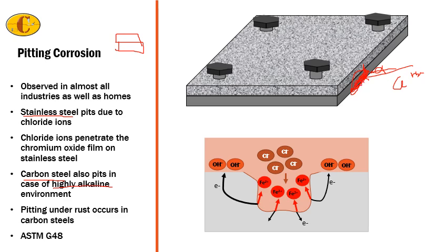In the other parts, however, the chloride can still continue going. So in this small part, you have the chloride reaching the corrosion site and reacting even more. In this case, that particular area will continue to grow while the other areas will start supporting the cathodic reactions. As a result, you have a pit-like structure formed, and this is the start of a pitting process.